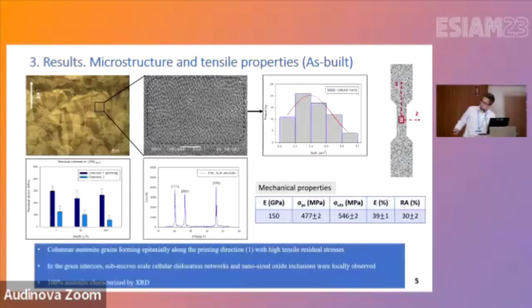And here we can see the X-ray diffraction pattern. It shows that there are only austenitic diffraction peaks. And here we are introducing the mechanical properties from left to right: elastic modulus, yield strength, ultimate tensile strength, deformation and reduction of area obtained in the as-built condition after the SLM process.